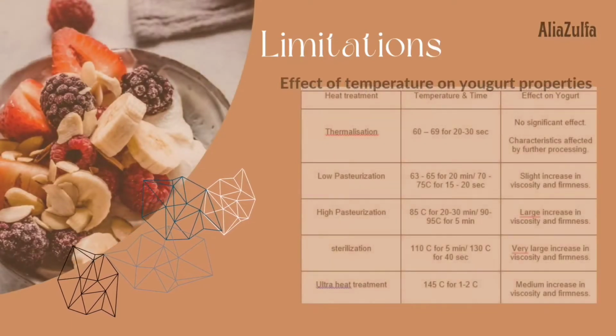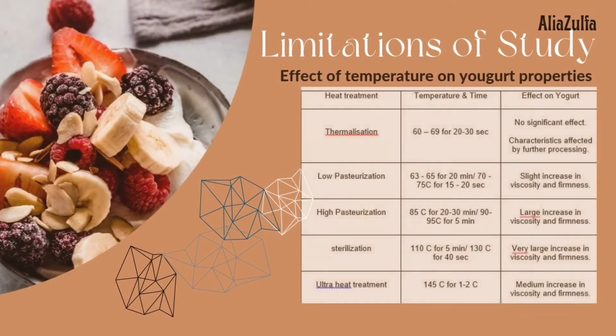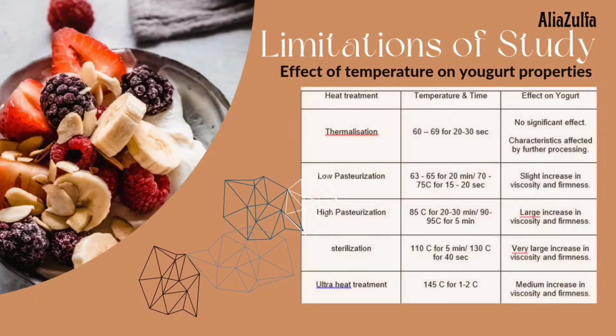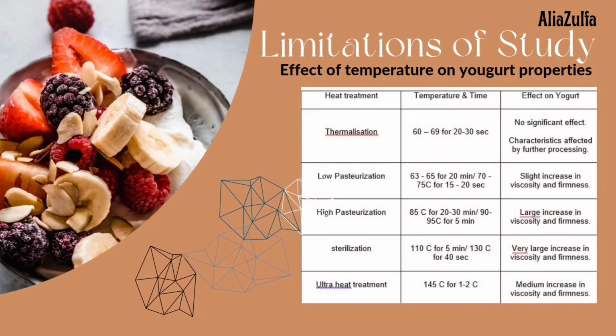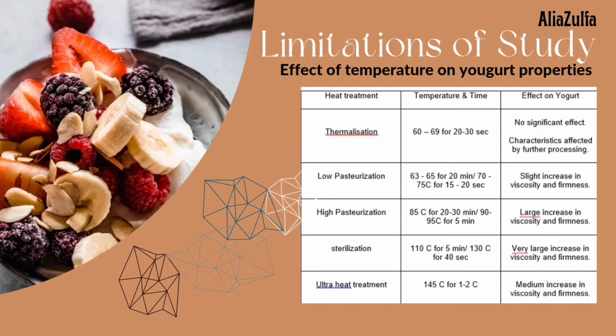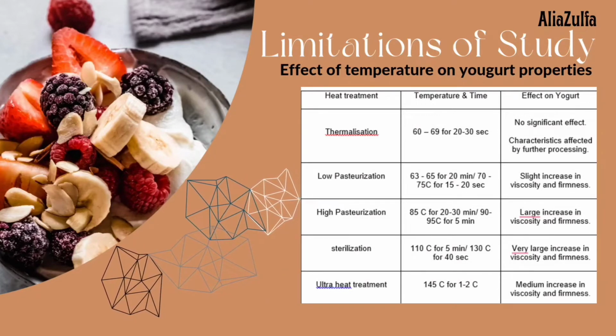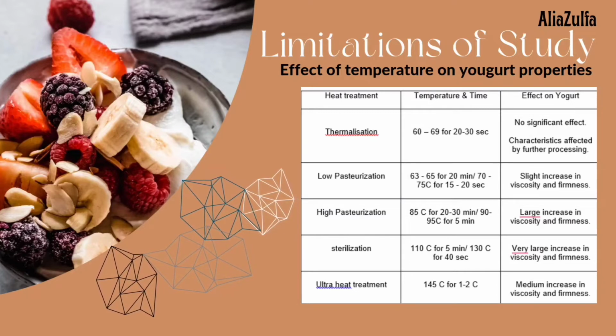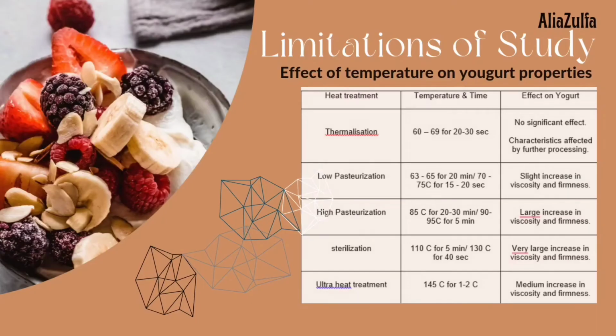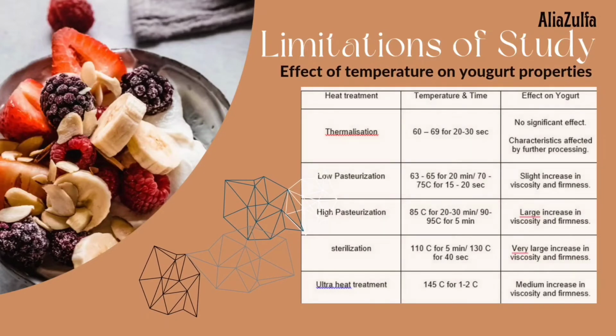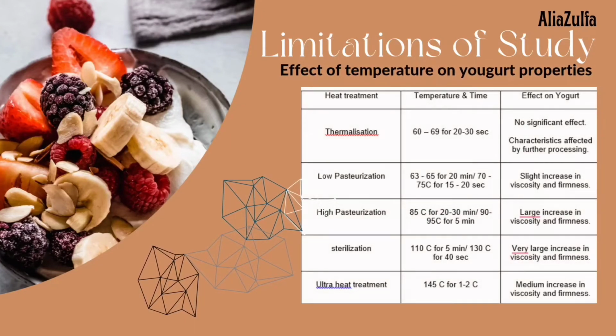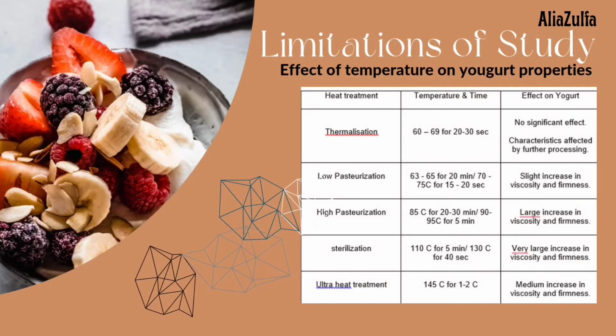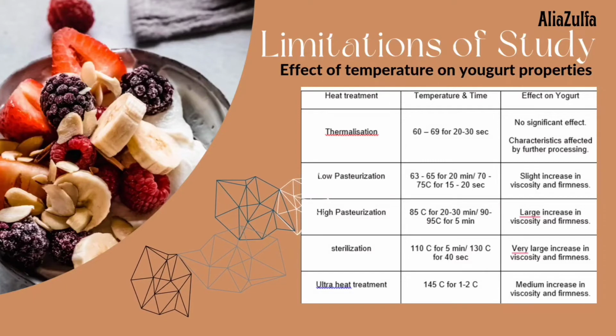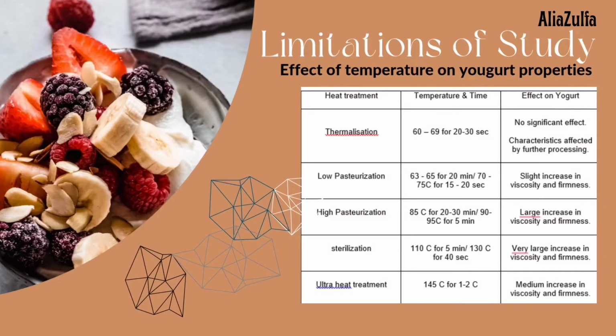Okay, now we discuss the limitation of study. Here, the effect of temperature on yogurt properties: heat treatment, temperature and time, and effect on yogurt. Okay, now we go to the first heat treatment, thermalization. For thermalization, the time and temperature we use is 60 to 69 degrees Celsius for 20 to 30 seconds. The effect on yogurt is no significant effect and characteristic effect by further processing. Second, the heat treatment is low pasteurization. The temperature and time is 63 to 65 degrees Celsius for 20 minutes, or 70 to 75 degrees Celsius for 15 to 20 seconds. The effect on yogurt is a slight increase in viscosity and firmness.